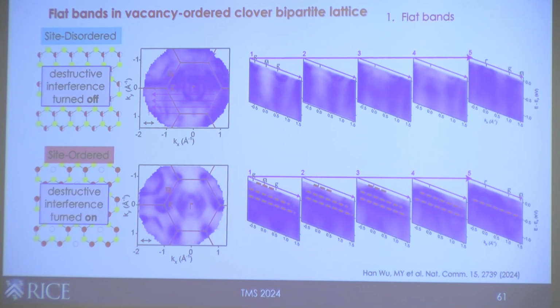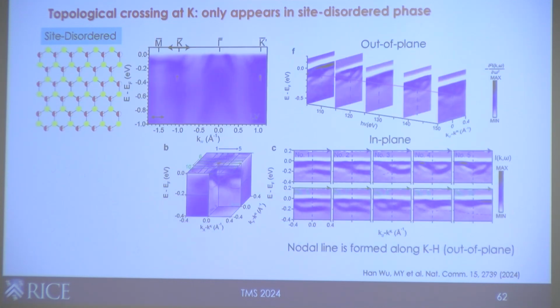Okay, I'm going to digress a tiny bit because there's something interesting associated with the other phase, even though this one doesn't have flat bands. It turns out at the K point, there are these topological crossings due to the global symmetry. Just to show you the ARPES results for this: at the K point, there's a band crossing. You see that for all kz.